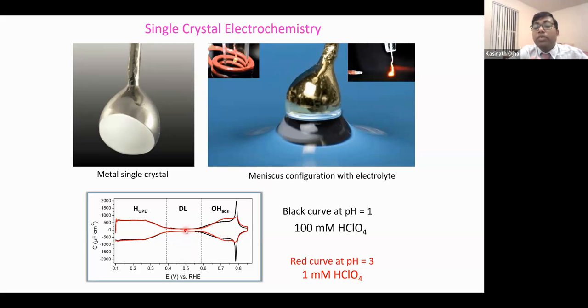And if we need to tune a little bit the pH of the electrolyte, because the potential PZC is independent of pH. But if you do measurement with respect to RHE, everything shifts, but the PZC doesn't shift. So in that case, our pH is 1 and 3, and the known PZC should lie right in between here. And so therefore, at low ionic strength, we should see a capacitance minimum right at this place. But instead of that, we did 1 millimolar, we don't see a minimum.